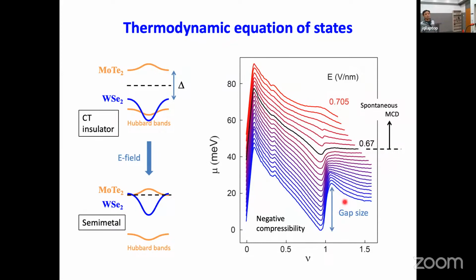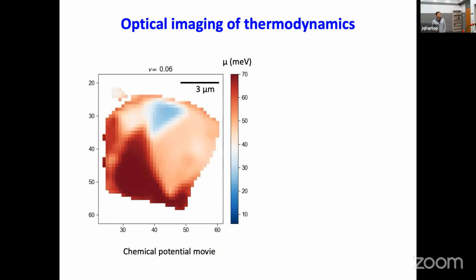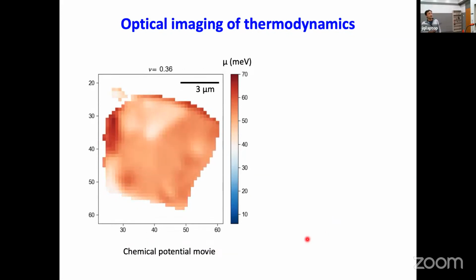And finally, you can read out the gap size of the insulating state by just looking at the size of this jump in the chemical potential. So you can directly read out the chemical potential jump. Here I'm showing a movie of the chemical potential map as a function of the filling factor in this sample.